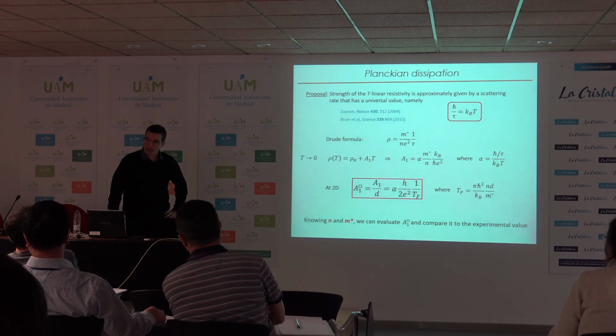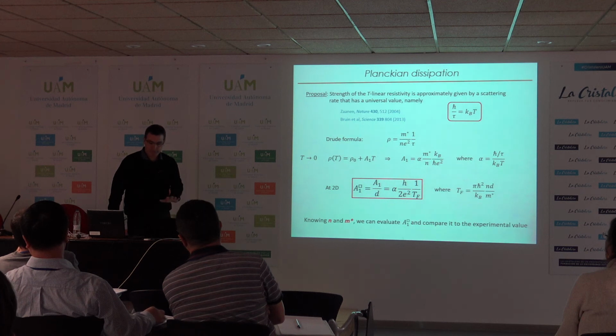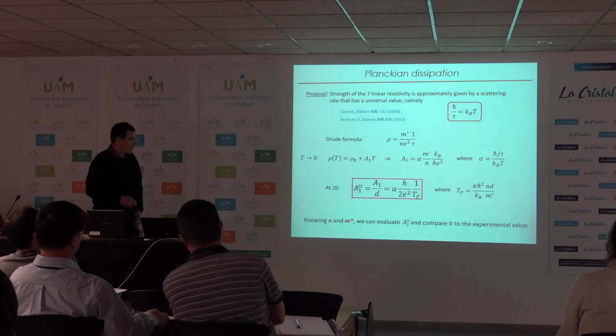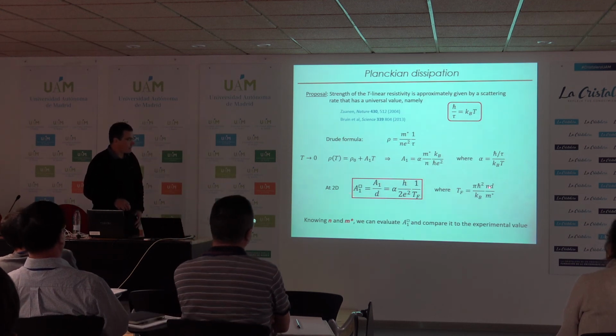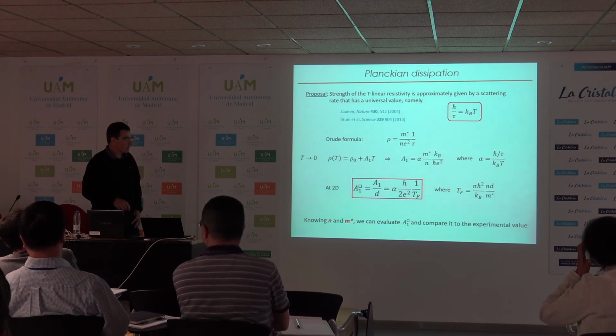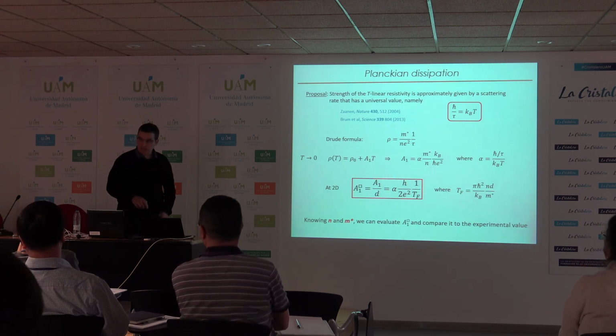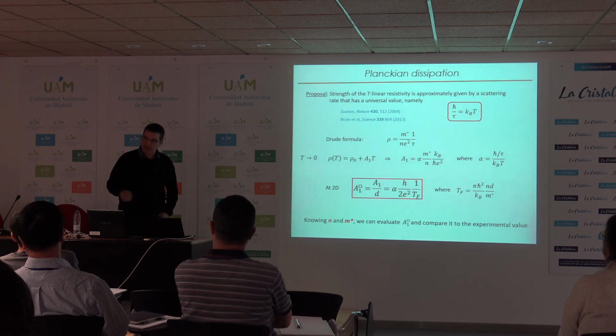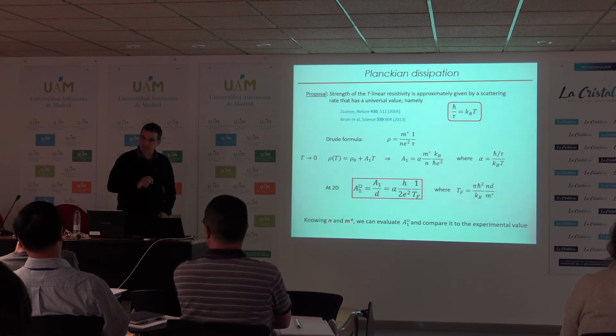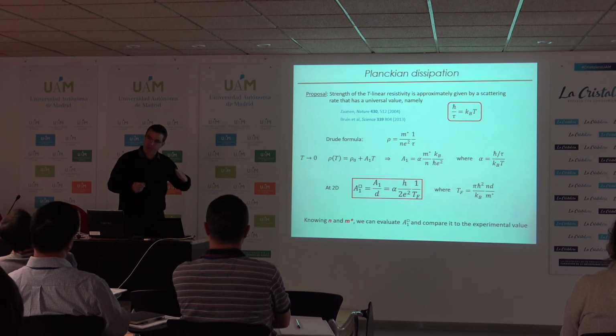If you assume the Planckian dissipation limit, and you work with the Drude formula, this A1 coefficient is given basically by the ratio of m star over n. And m star is changing with doping, but if you fix the doping, you should always have the same coefficient. Which is the case. So this is the slope, A1, experimentally observed.